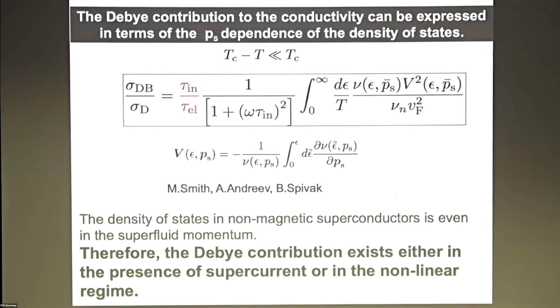This is the first place, it's a new formula. It is correct for any superconductors, S, P, D, arbitrary disorder. So the mean free path could be larger or smaller than the coherence length. It is a mean field formula, but it can be generalized, I think, for quantum fluctuations. It hasn't been done, but I think the generalization is kind of simple. But anyway, this is the main message here: the ratio between the elastic and inelastic relaxation time. Now, from this formula, you see the following, that this derivative of the density of states over superfluid momentum should be not zero. So the density of states is a scalar.